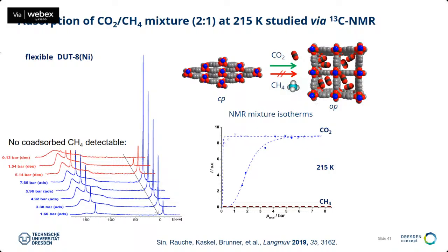So you can basically quantify the gas phase and the adsorbed species at the same time. And you can also quantify the adsorption isotherm from the integration of the NMR signal. And you see that there's a pure uptake of CO2. There's no uptake of methane gas, given the detection limits of the NMR spectroscopy. So the curve for methane is totally flat. Normally you would expect the methane to be here, but we only see it in the gas phase. So it is only selectively the CO2 that is taken up, as proven by this in situ experiment.